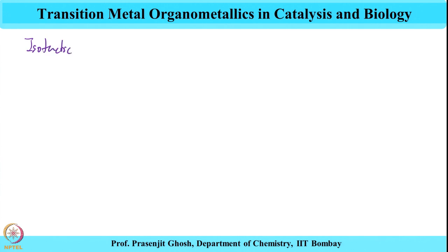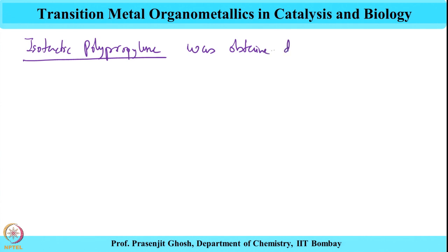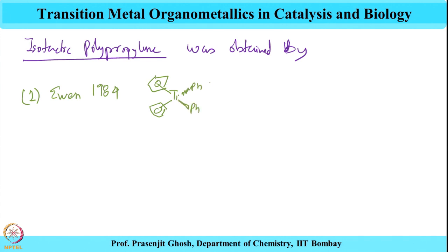So, isotactic polypropylene was obtained first by Ewen in 1984 in presence of diphenyl titanium catalyst at minus 30 degrees centigrade. So, the low temperature was used so that more ordered formation could be obtained, and the second